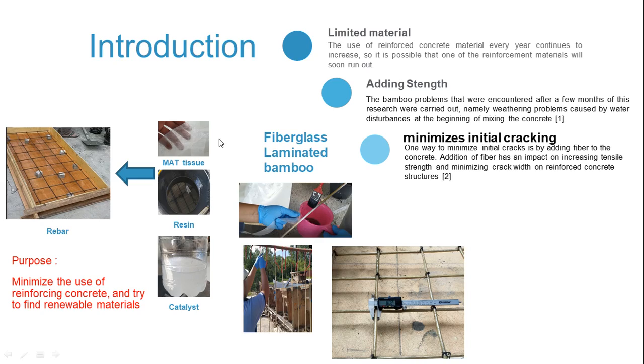In this picture we can see the components: mat tissue, resin, and catalyst. We mix these components and call the result fiberglass. The bamboo is coated using the fiberglass. This layer is joined with the bamboo to minimize the occurrence of initial crack openings in the concrete, since we know concrete has a weakness in tensile value.